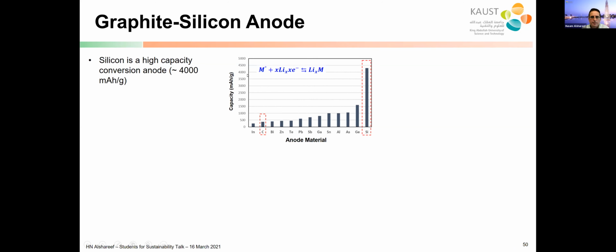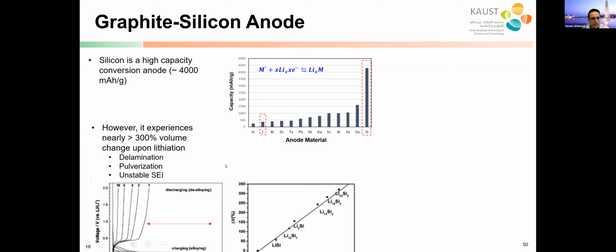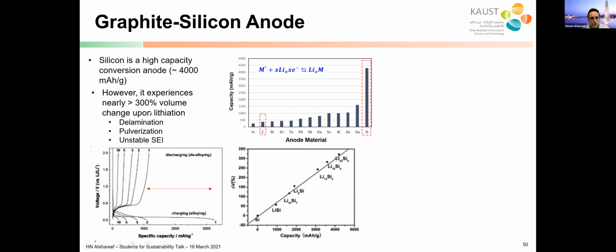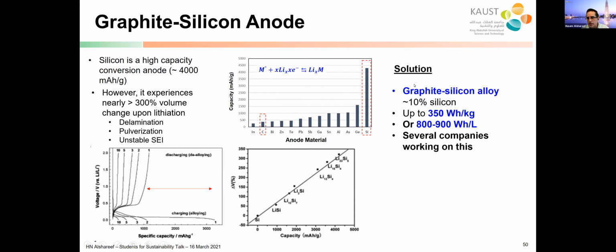The graphite silicon anode: if you look at the silicon here, silicon is supposed to give you above 4,000 milliamp hour per gram. But we cannot really use silicon completely because there's a large volume change. And if you look at the left in this curve down here, you see that after the first cycle, there's a significant drop in the energy. The battery is not stable. So what people are opting for is a graphite silicon alloy using up to 10% silicon. This could give 350 watt-hour per kilogram, and many companies are actually working on this. So this is realistic.